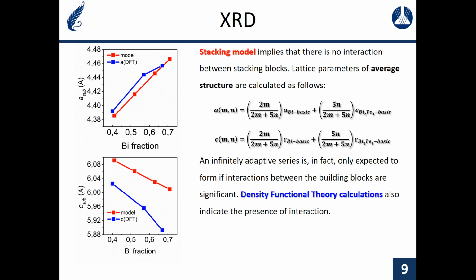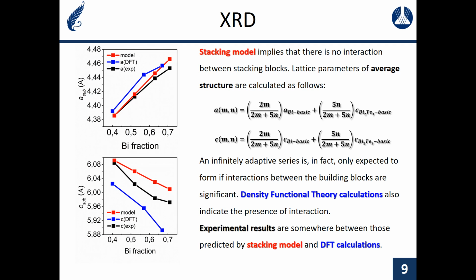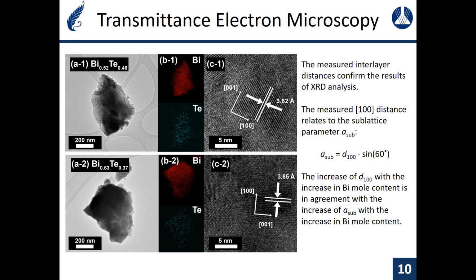On the other hand, structure optimization with density functional theory has disclosed the interaction between the stacking blocks, manifested especially in the shrinking of C lattice parameter. Our experimental results fall in between those predicted by DFT and the stacking model, thus indicating the interaction between the building blocks of the superlattice. The refined lattice parameters were in the agreement with the microscopy data, as shown in this slide.